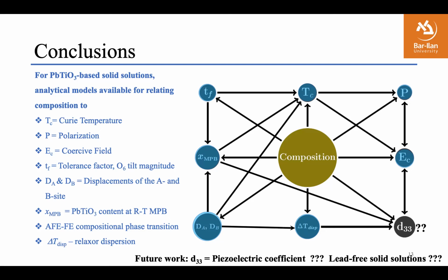So thin films, I think, will be exactly the same, like let's say the TC of a thin film. The only question is what happens when you strain. Actually, in this paper, we show that we can modify the displacement based on strain using some sort of relationship, so you can more or less predict the evolution of TC and therefore the coercive field for the thin film as you strain the material. Essentially, what this says is that your collective properties, like coercive field and TC, again without looking at grain boundaries and things like that, are governed by the polarization of the material. So if you know how polarization evolves with strain, you know how TC and coercive field will evolve, to first approximation. Okay. Very interesting.